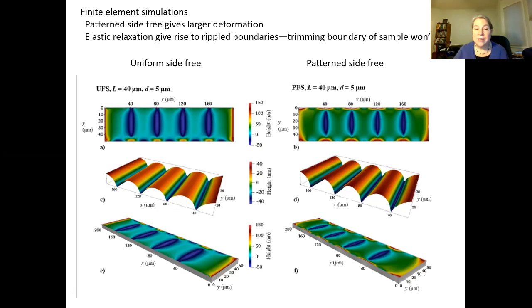And so if I were in the lab and I fabricated one of these and I said, wow, the middle of my sample looks beautiful and perfect, but the edges are kind of a mess, I would trim it. I would cut it. And you know what? It would wrinkle up just the same. It's an elastic relaxation. It is not because something bad happened when you polymerized the material at the edge of the sample. It is fundamental to the elasticity. We also find that if the pattern side is free, we get a bigger deformation than if the uniform side is free. That agrees with the experiment.